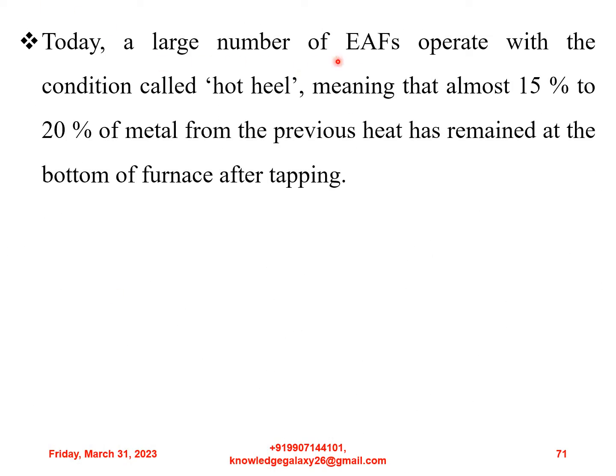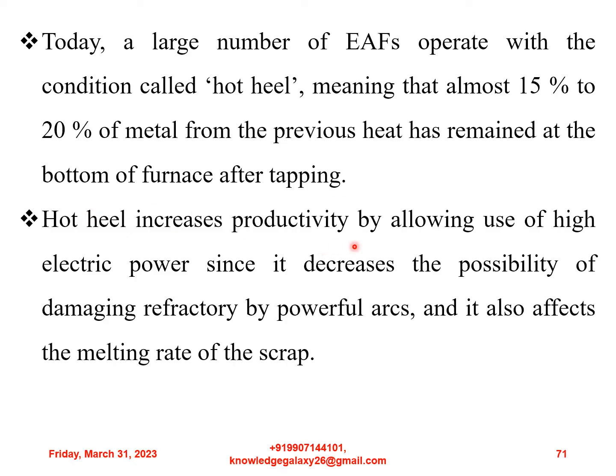Today, a large number of electric arc furnaces operate with the condition called hot heel, meaning that almost 15% to 20% of metal from the previous heat has remained at the bottom of the furnace after tapping. Hot heel increases productivity by allowing use of high electric power since it decreases the possibility of damaging refractory by powerful arcs, and it also affects the melting rate of the scrap.